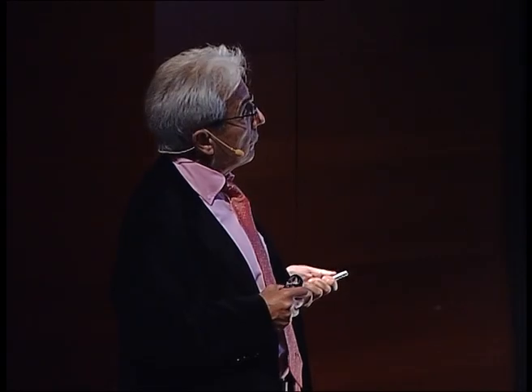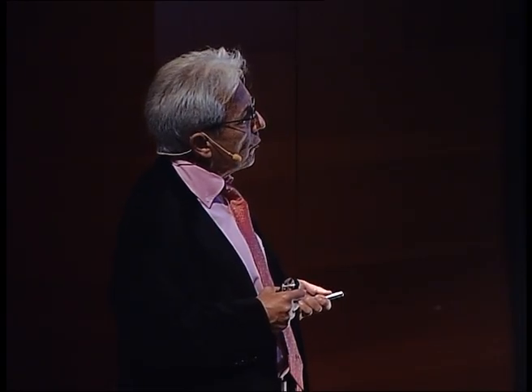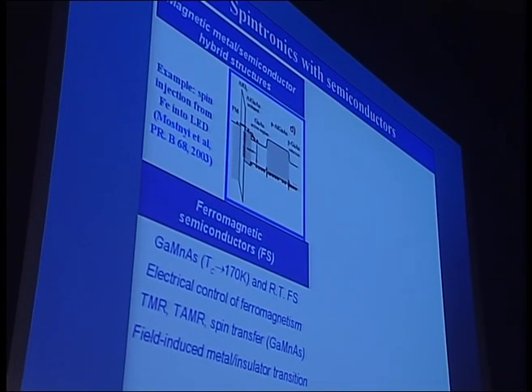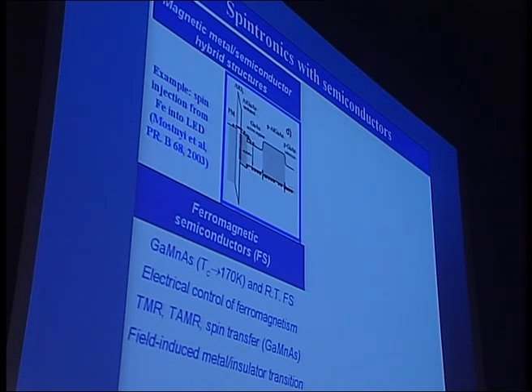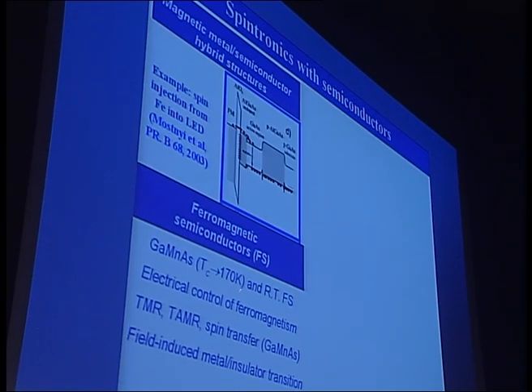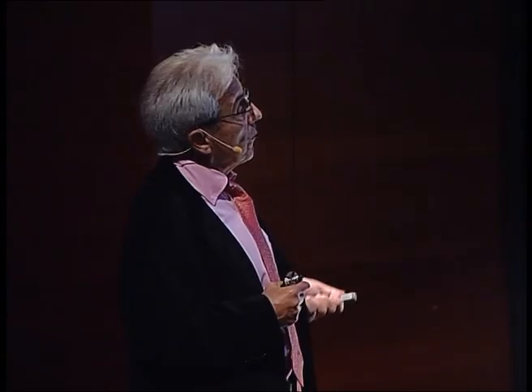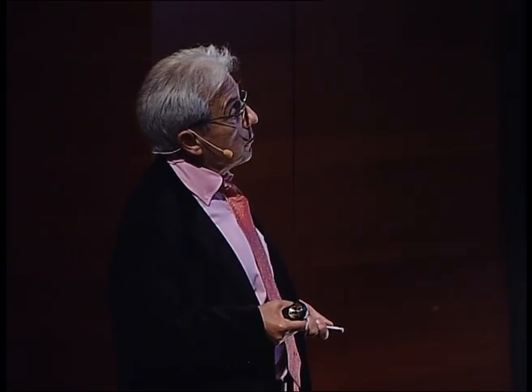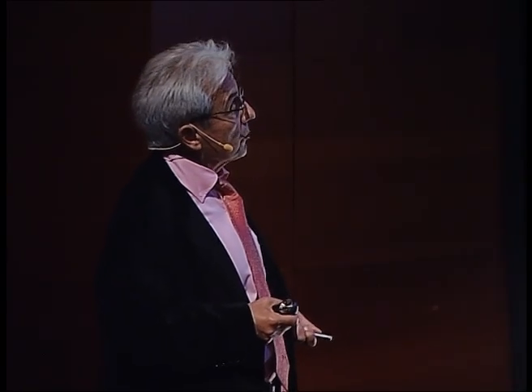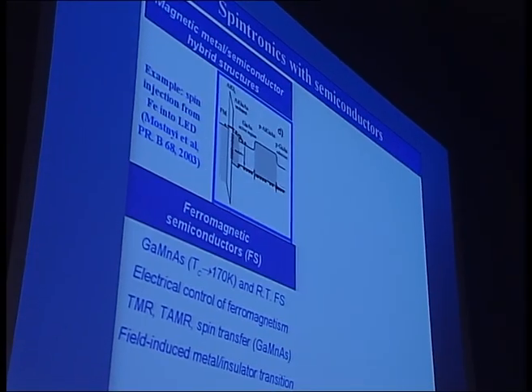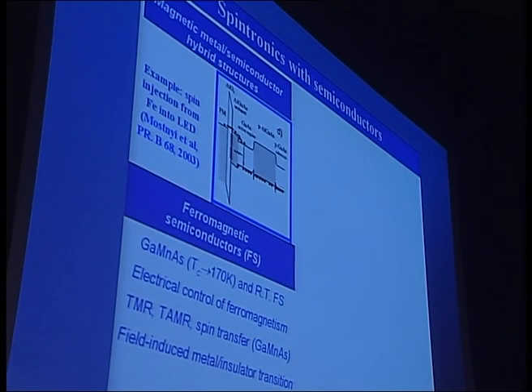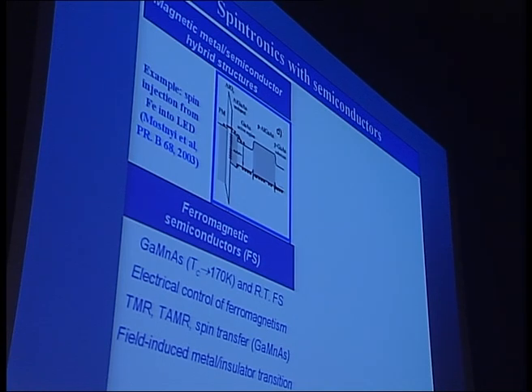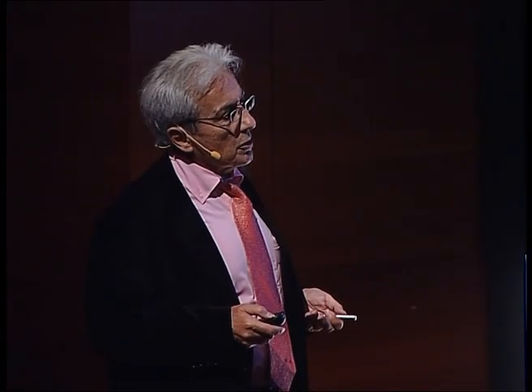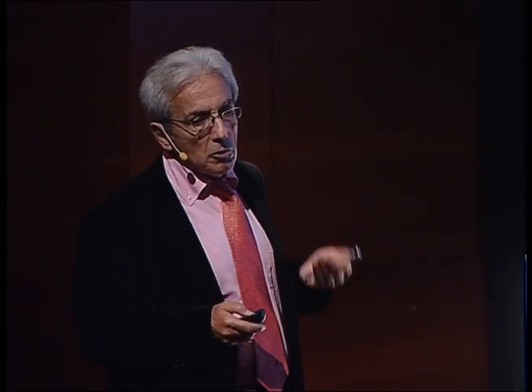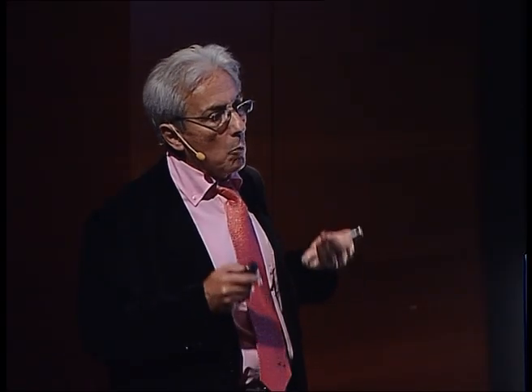I have showed some results of spin transfer, of switching of magnetization with a tunnel junction. They show large TMR results, but the Curie temperature, the temperature below which the material is ferromagnetic, is only 170 Kelvin. So for the moment, this sort of compound cannot be used for application. Room temperature is needed for most applications. And so the challenge is finding also other ferromagnetic semiconductors working at room temperature. Several announcements have been made. I would say that the situation is rather confused on this front, actually. At the moment, there is no ferromagnetic semiconductor really working at room temperature.